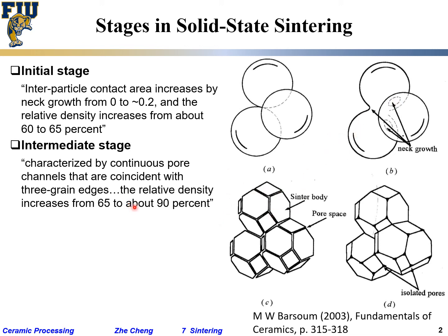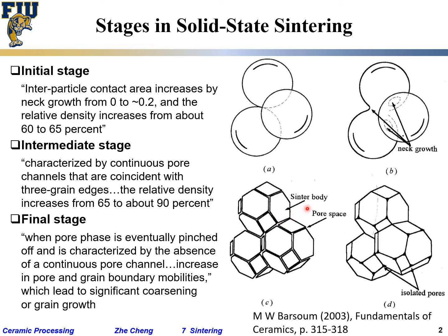During the intermediate stage, these are highly conceptual and rough estimates. Density increases but grain size doesn't increase too much under ideal conditions. Towards the end, the connected pores become isolated — located only at the corners where particles touch each other. At the same time, the particles become larger due to unavoidable grain growth towards the end. From the initial stage to roughly 80–90% density the grains hopefully don't increase too much, but towards the end grain growth occurs and the pores become isolated.